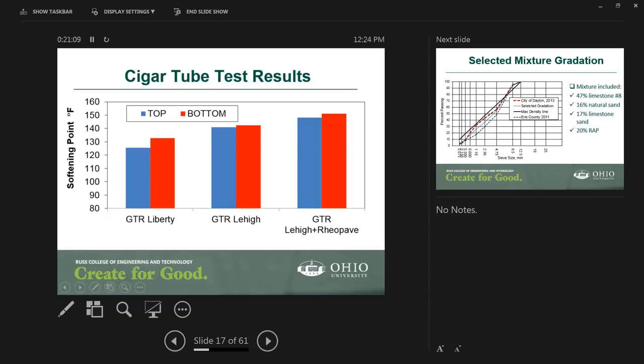All the specifications allowed a 10 Fahrenheit difference between the bottom and top parts. Currently, I think the most current ODOT specification allows 18 Fahrenheit, so it's higher. But in all cases, we did not really see any difference in terms of separation based on those lab binders. We have seen that for the Liberty, which is a coarser GTR as compared to the Lehigh, there was more separation, and I think it makes sense because if you have coarser particles of a material, then it will settle faster. This is basically Stokes' law.